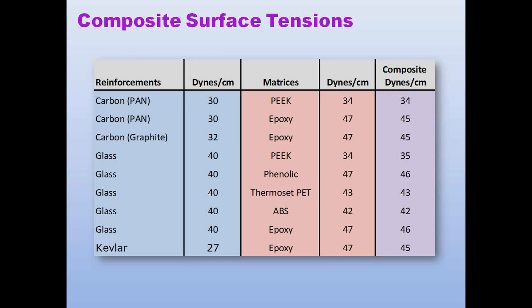The same thing applies with these other materials, most notably Kevlar. It has a very low surface tension at 27 dynes per centimeter, but the epoxy matrix is the determinant of how it's going to get functionalized.